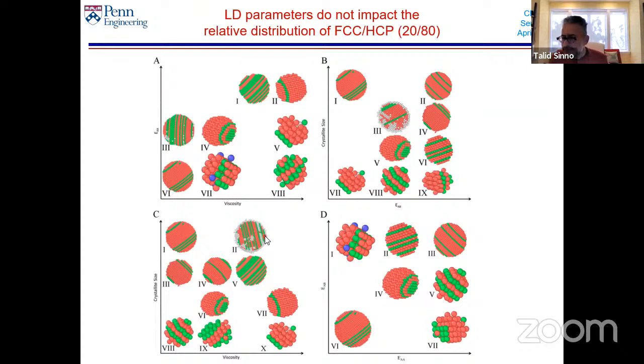So we started asking, well, why do we see almost exclusive FCC in the experiments, but we see a mixture in simulation? So we started varying different things. We were doing Brownian dynamics. We varied the diffusivity through the viscosity. We still see a mixture. We varied the crystallite size. Small crystallites, large crystallites, again, it's a mixture. So crystallite size doesn't affect anything. The viscosity doesn't affect anything. We varied the relative interaction strengths. Doesn't affect anything. And as you can see, most of these, although it's random, it's mostly red, which means it's mostly HCP. It's about 80% HCP, 20% FCC.